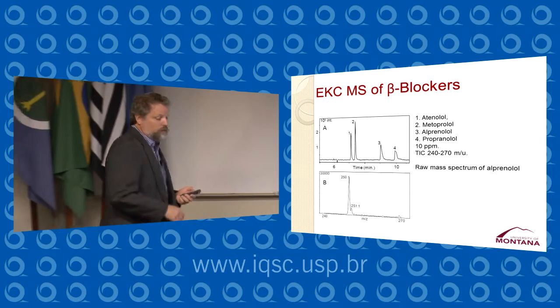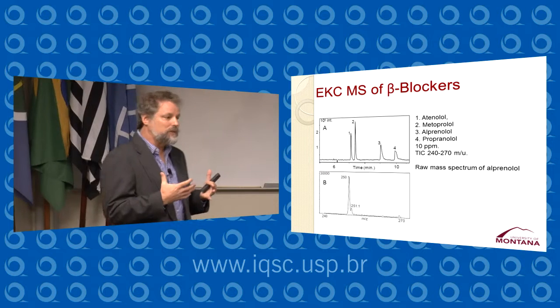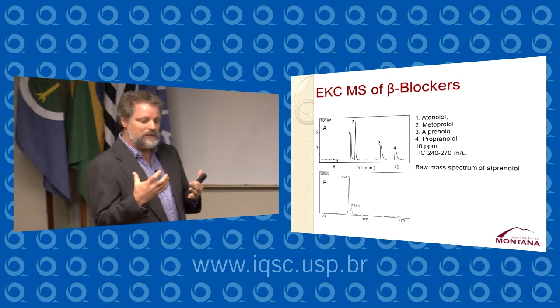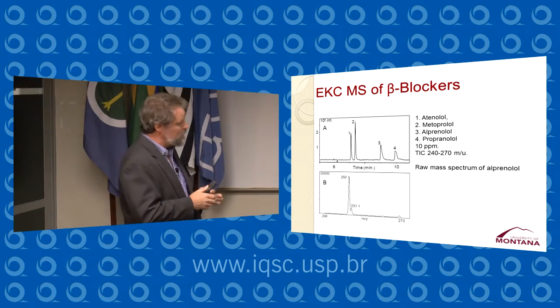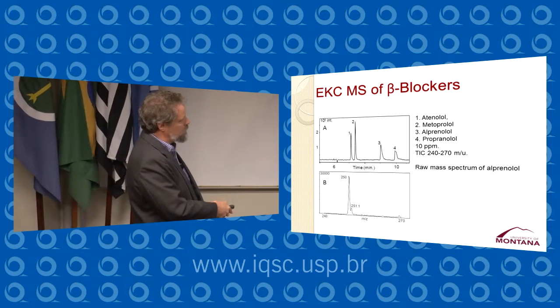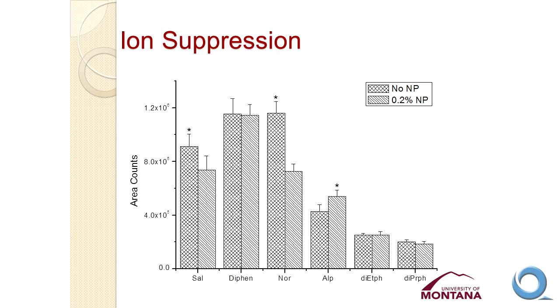And in fact, if we look at the extent to which we see any kind of ion suppression, so what you're worried about when you add an additive like this is that it will suppress ionization of your analytes. So what we're looking at here is the signal from the mass spectrometer without nanoparticles and then with nanoparticles for salbutamol, diphenhydramine, nortriptyline, alprenolol, diethyl phthalate, and dipropyl phthalate. When we look at these results, we see a couple of cases where we do see significant loss, statistically significant loss in the signal. But in most cases, we see no significant change in the amount of signal that we achieve. And so, in general, these nanoparticles work quite well for mass spec detection.